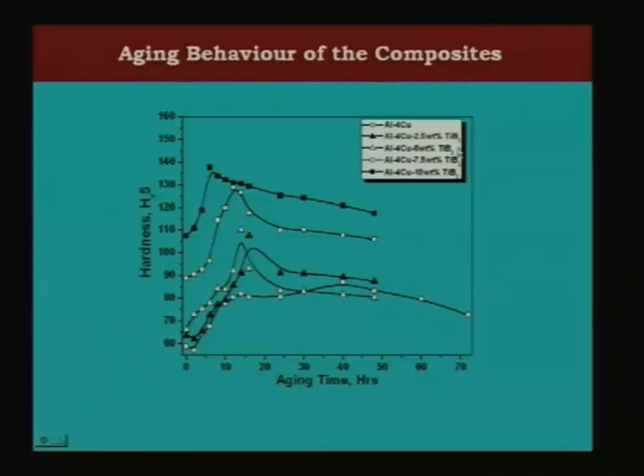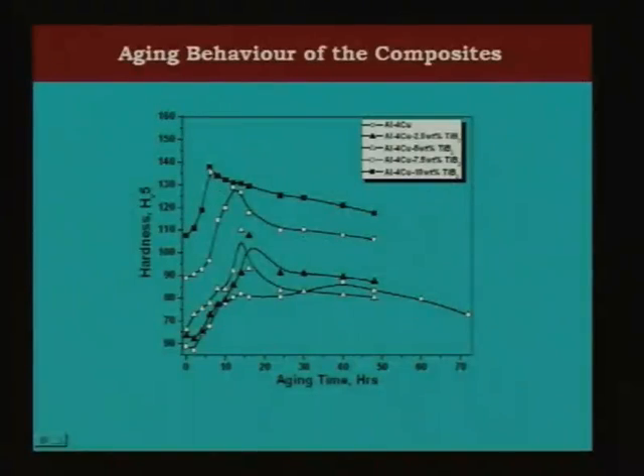In addition, another important thing that you can see is that the peak hardness is achieved at a lower time. That means the aging process is hastened, or the aging process becomes faster. Why? Because the presence of these TiB2 particles act as nucleating sites for the theta double prime or theta prime or the GP zones to form, and because of which, for example, if you take 10% TiB2, the peak hardness is reached within almost about 6 hours, whereas without any TiB2, the peak hardness takes almost about 12